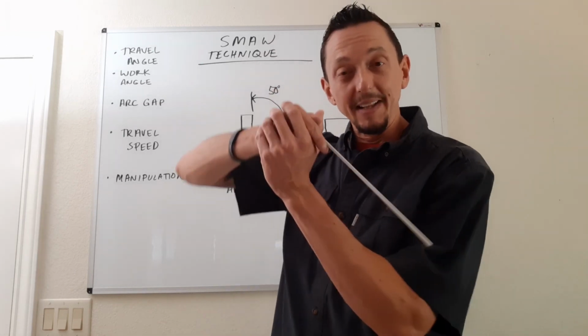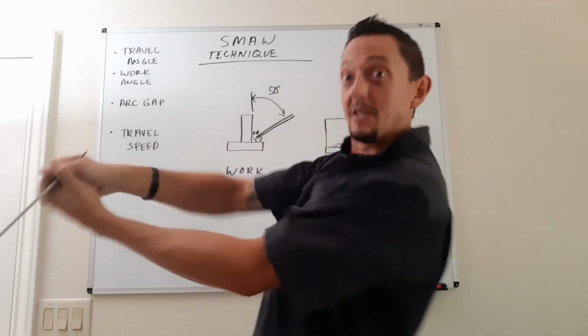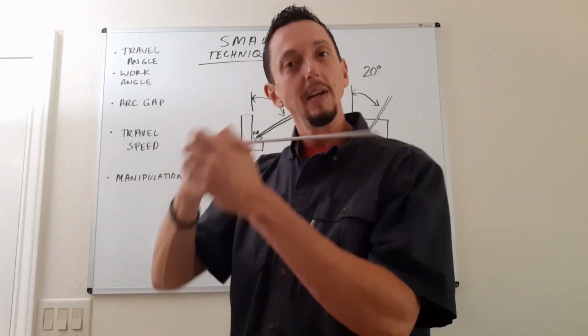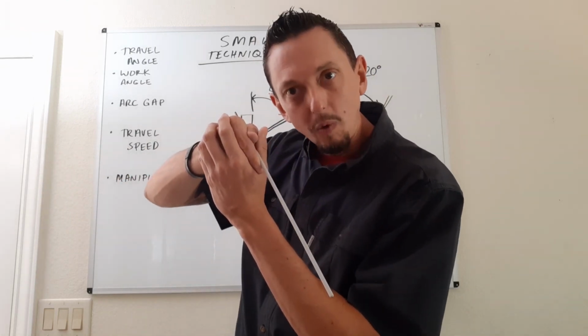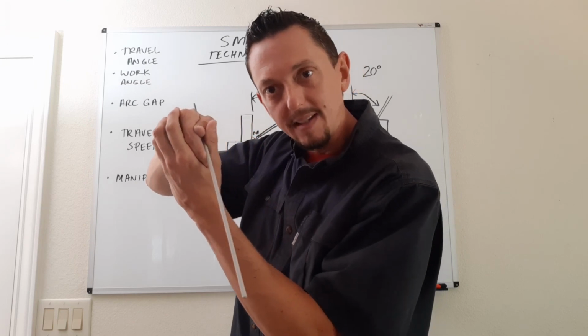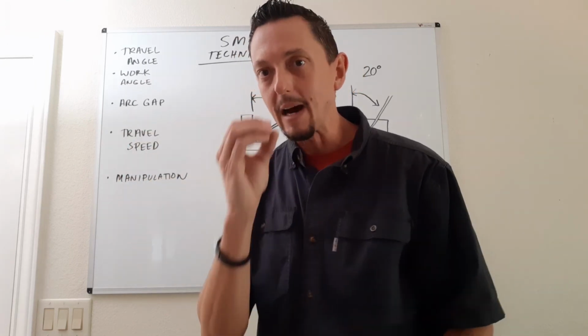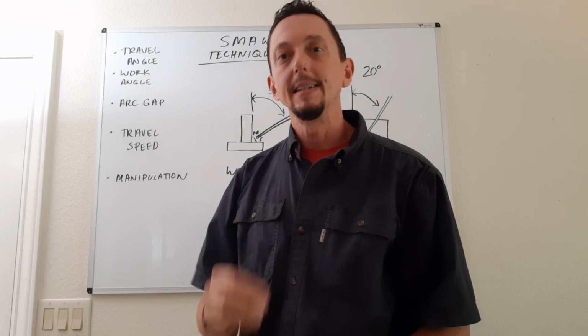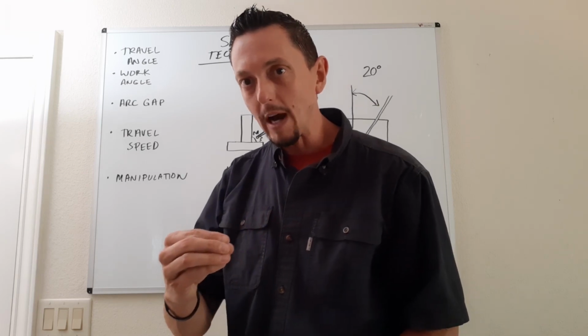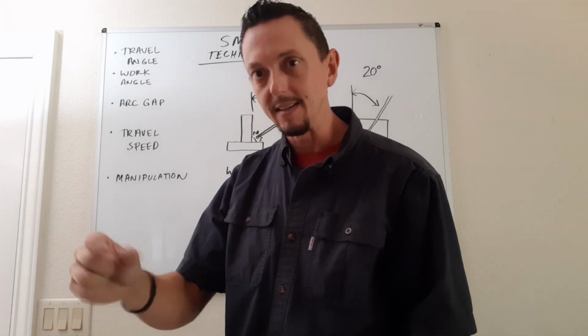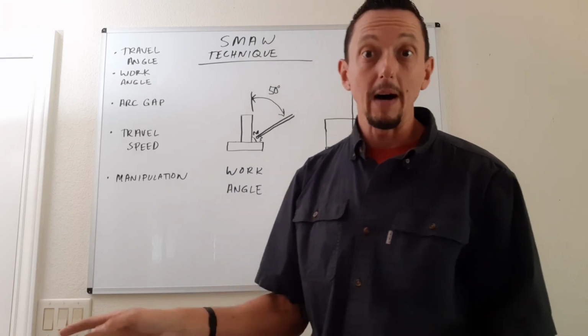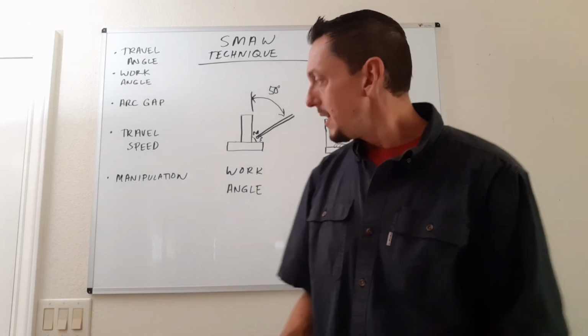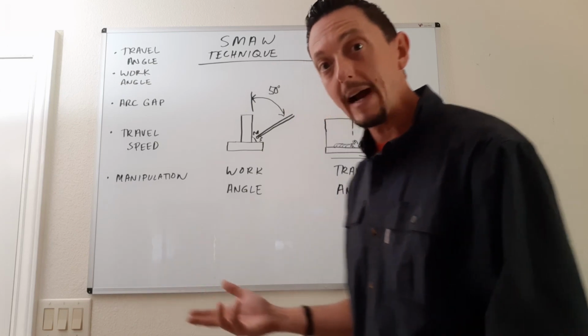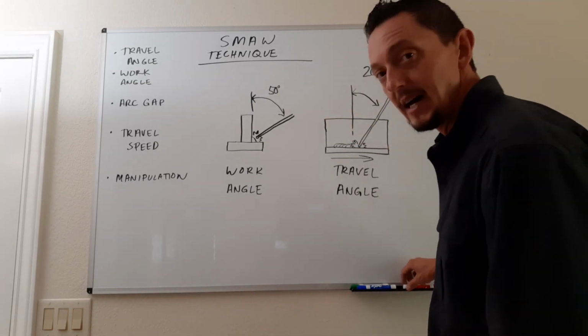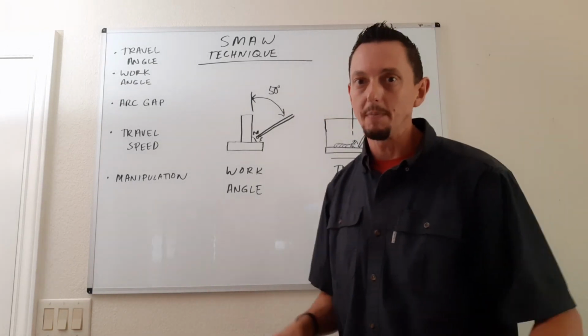So what I see a lot of new welders is once the arc starts, they just want to get to the end of that weld. Get it started, let that weld pool fill up, keep a nice, slow, steady pace, let that weld pool form, and try to maintain that same travel speed to keep that size consistent of your weld throughout the entire weld. Okay, so you can also take a look at what you're actually seeing in the weld when you're done and make a determination based on that.